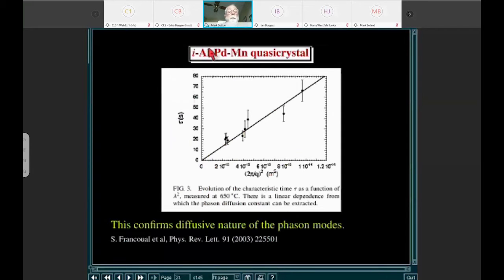Here is an example that's more at wide angle scattering. Here they're looking at quasi-diffraction peaks from quasi-crystals. So they're sort of like a Bragg peak associated with the scattering from quasi-crystals, and you can look just off the Bragg peak. So this is the thermal diffuse scattering around quasi-crystal peaks. And you can measure the time constant as a function of wave vector squared. So the slope of this, again, is diffusion. So this is showing you that the phason modes, which are the fluctuations of the incommensurability of the quasi-crystals, obey a diffusion equation.